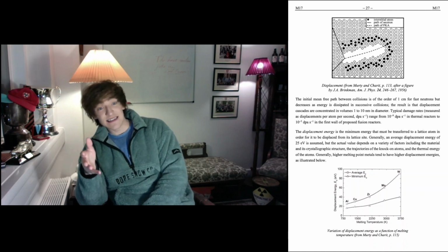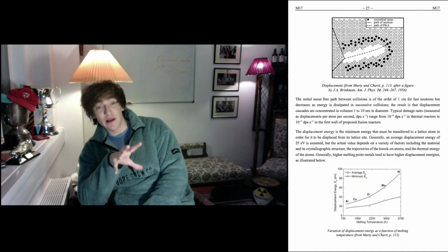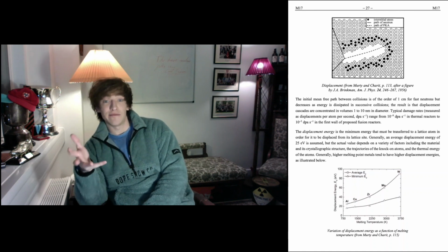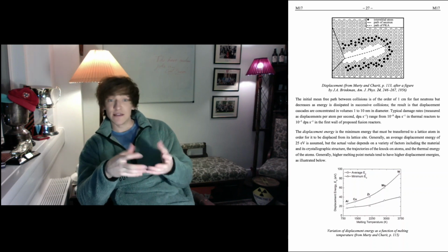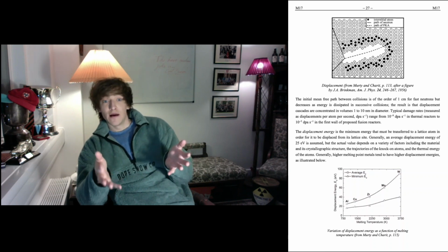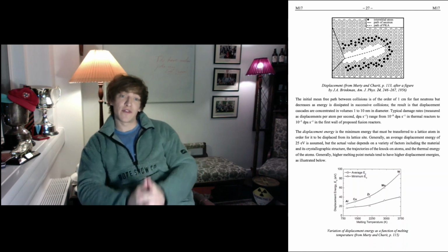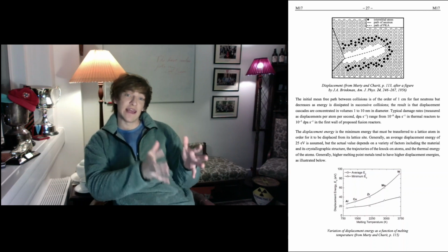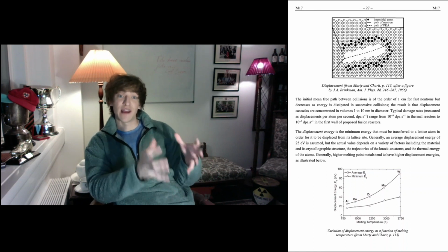Well, in practice, those Frenkel pairs that are produced in displacement cascades can recombine and restore the equilibrium structure. And so many do. However, some defects will often remain. And over time, those defects that have survived will accumulate to cause what we're going to see as radiation effects. Okay, so that's what a lot of the course will focus on, the radiation effects.